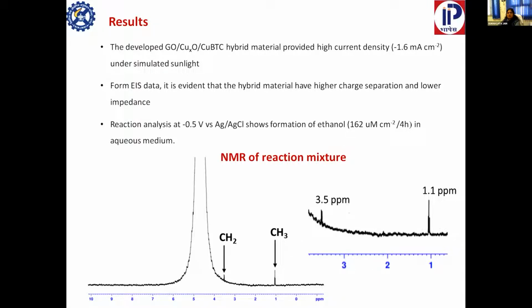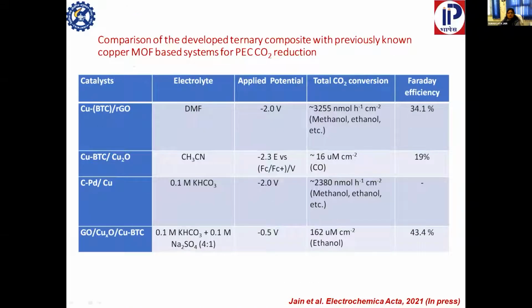So I hope we will soon complete this work with an established mechanism, and with the designing and fine tuning of the chemical material for further development of the methodology for selective conversion of CO2 to ethanol or higher alcohols. If we look at the literature, only a few systems are known which provide alcohols, but our system is selectively providing ethanol, which is not reported in the literature, with much higher Faraday efficiency than the literature ones.